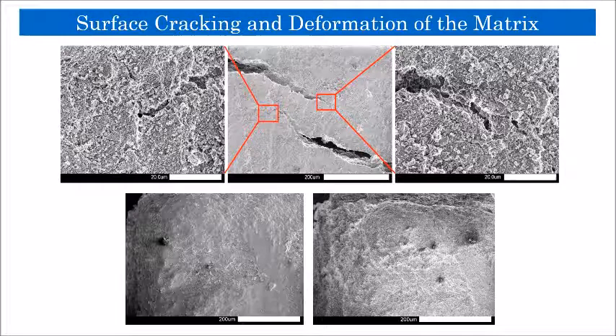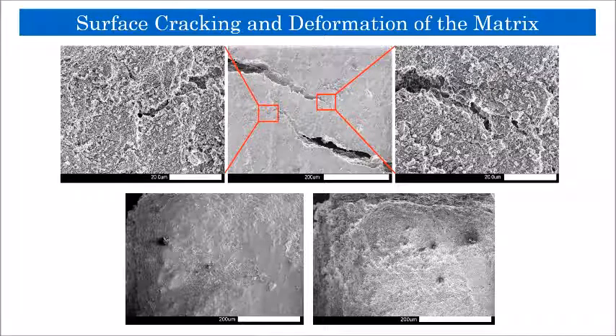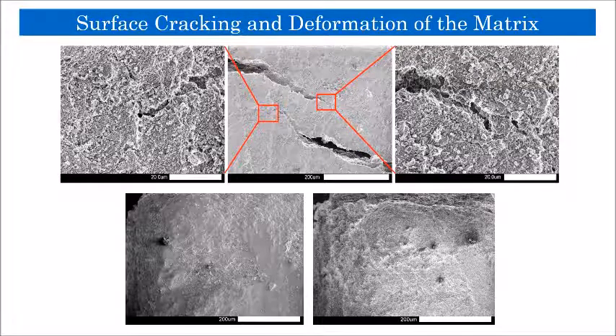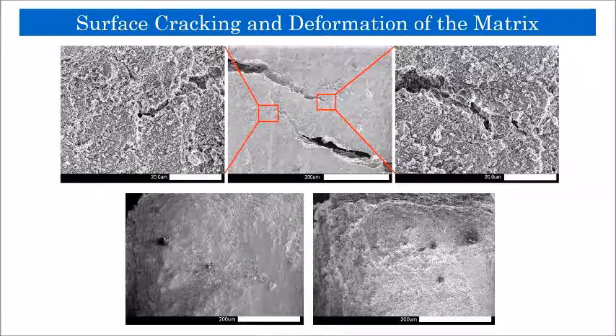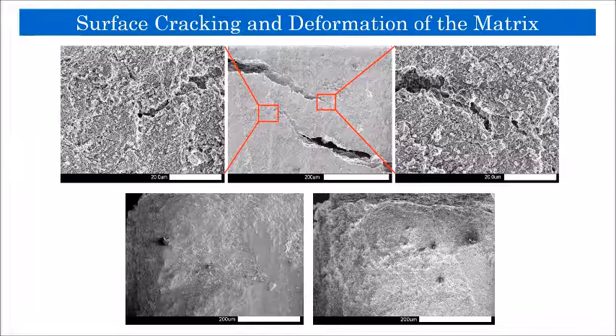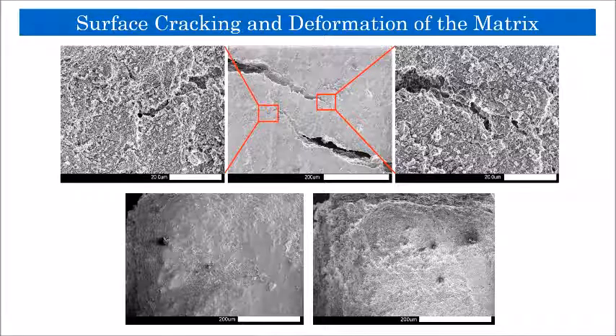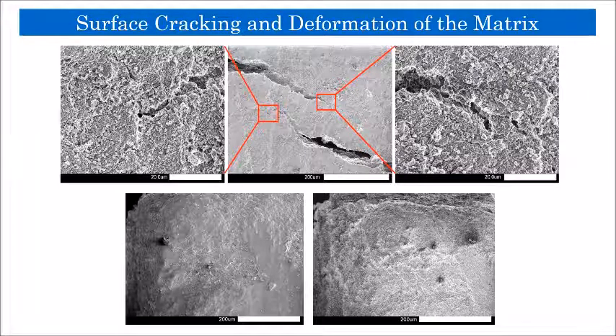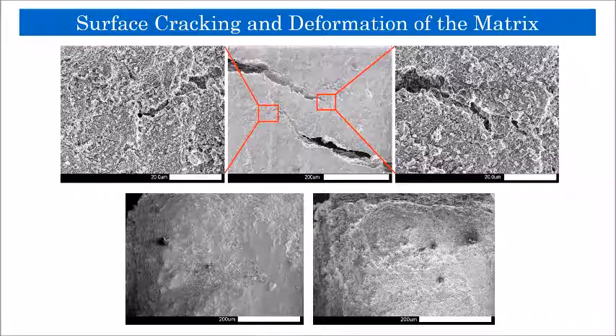Release of the crystalline water as well as micro-scale ablation can be considered as the main causes of this microstructural change. Moreover, both of these factors can be considered as contributing factors to the observed mass loss.